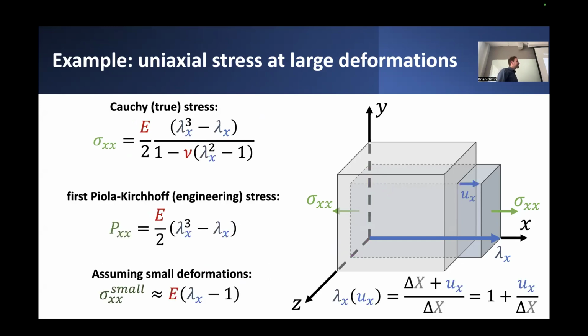Now, what's interesting is that we can compare all of these different measures of stress as we've previously developed. We can look at Cauchy stress, that force per unit of deformed or final area, expressed exclusively in terms of this axial stretch ratio. We can also look at engineering stress, nominally defined in terms of these finite strain and stress measures, and it'll look almost the same. It just won't be divided by this extra term. So almost the same. And then finally, we can compare it against our classical linear elastic theory.